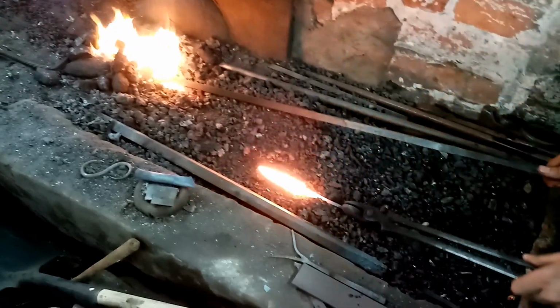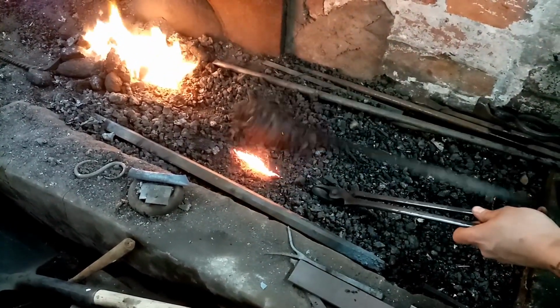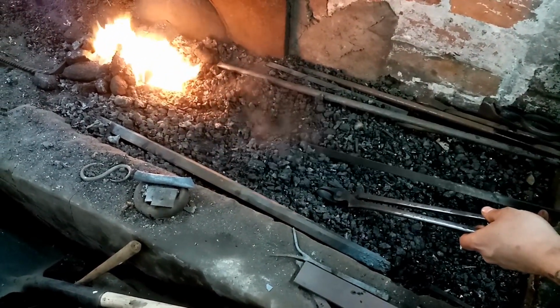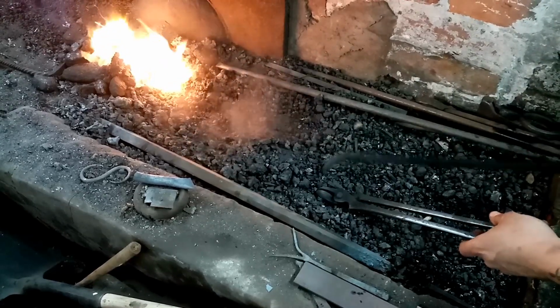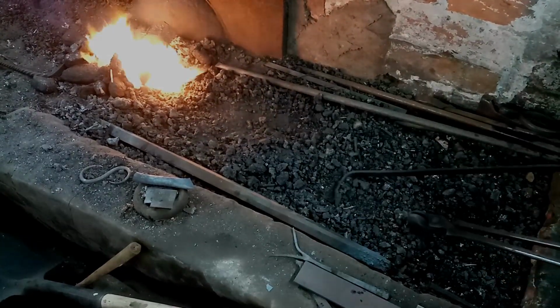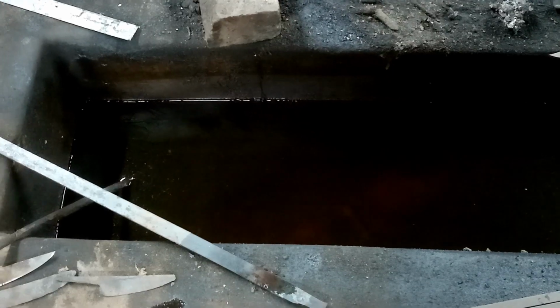So heat your blade up to above 880 degrees, hold it at that temperature for a while, usually 10 minutes in the forge, and then bury it in the ashes around your forge and leave it to cool slowly. That relieves the stresses. Once you have done that, you are ready to go on to hardening.